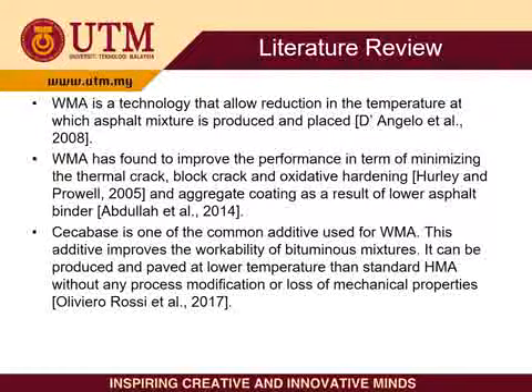WMA has been found to improve performance in terms of minimizing thermal cracking, block cracking, and oxidative hardening, as stated by Hurley and Powell 2005, and aggregate coating as a result of lower asphalt binder viscosity, as stated by Abdullah et al. 2014. For this study, we focused more on Cecabase, which Oliviero Rossi et al. stated is one of the common additives used for WMA. This additive improves the workability of bituminous mixture so that it can be produced and paved at lower temperature than standard HMA without any process modification or loss of mechanical properties.